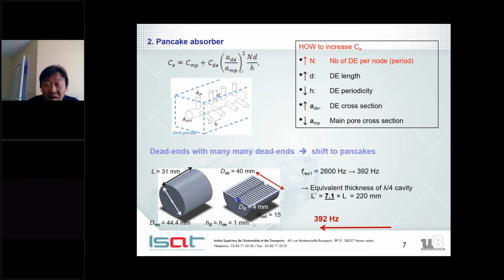So if we look at this expression, we need to increase the number. If we increase n, it's good. We need to increase the number of dead ends per node. We also need to increase the cross section of the dead ends and reduce the cross section of the main pore. But these two conditions are difficult to implement, because we cannot control these much. We can also decrease the periodicity, which is good for us, because it will contribute in reducing the thickness. And last, we can increase the length of the dead ends, but also we are limited because laterally we need to keep a good perforation rate.